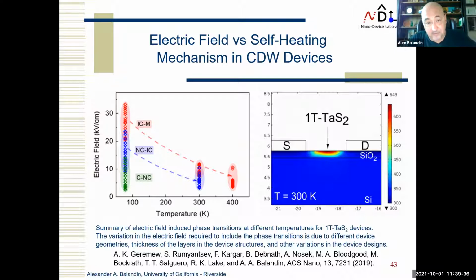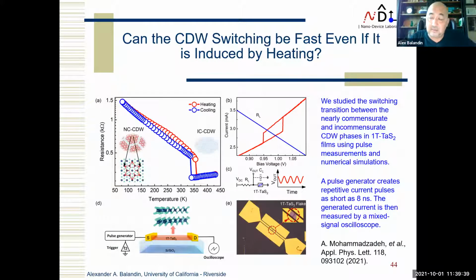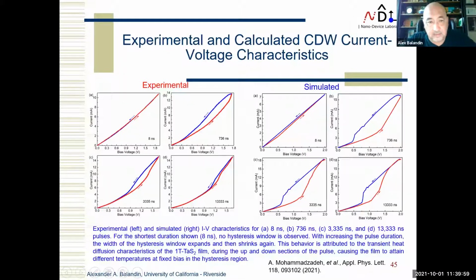And in this case, it might be a very fast device. But our question was, if this switching is driven by local heating, can it still be fast? We collaborated with a group at the University at Buffalo to prove that. For that, we sent them devices which were fabricated on special substrates, and they did pulse measurements, starting from a few nanoseconds and then increasing. On the left is experimental data, on the right it's our simulated data.